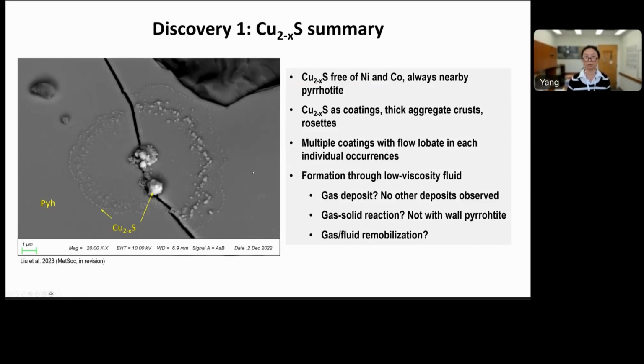So I want to show you this example as well, but as a summary, for this sample, it's actually very stunning because here is a fracture on the pyrrhotite wall, but we see these coatings, multiple coatings again, one very fine-grained, a second one, and then in the center, there seems to be the last part of this copper sulfide material. And for this one, most people on the call can probably resonate with this image, because if you drop a coffee drop on a table, when it dries, it looks like this pattern. I'm not saying this has to be the way it formed, but it does show some kind of fluid that's coming out and depositing the copper sulfide.